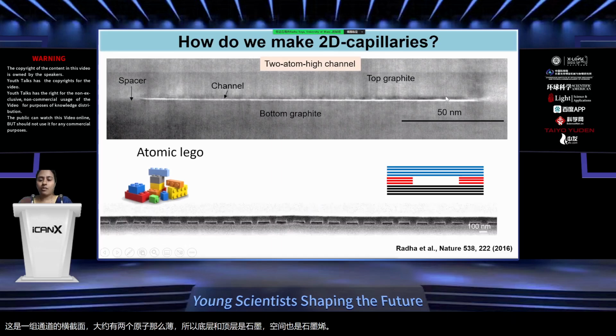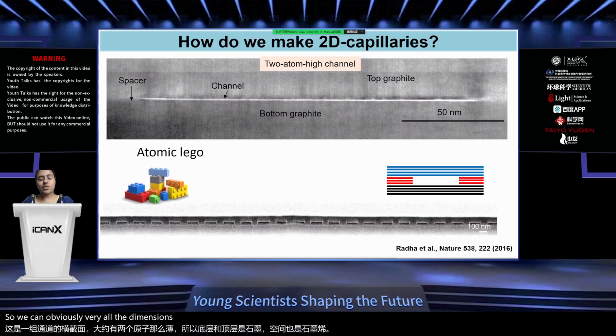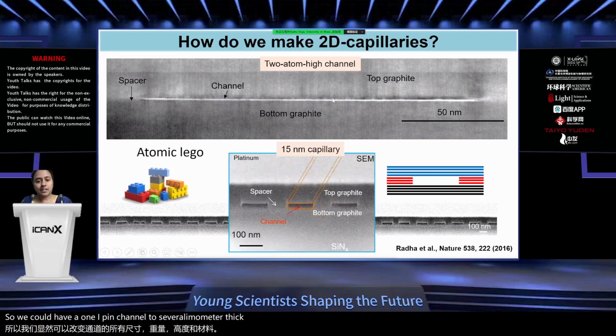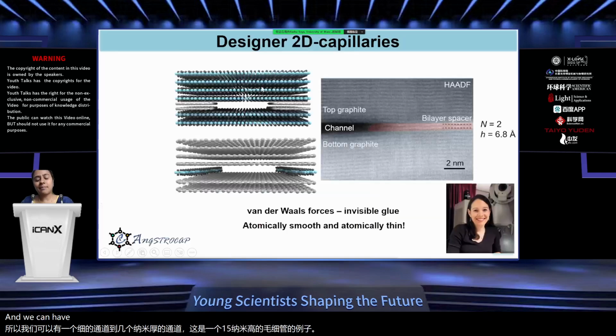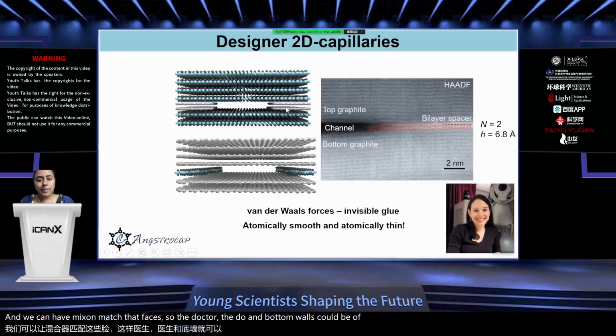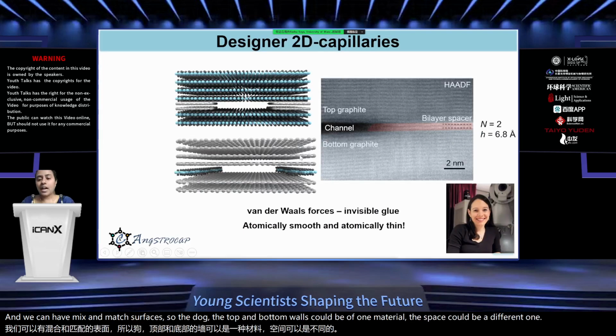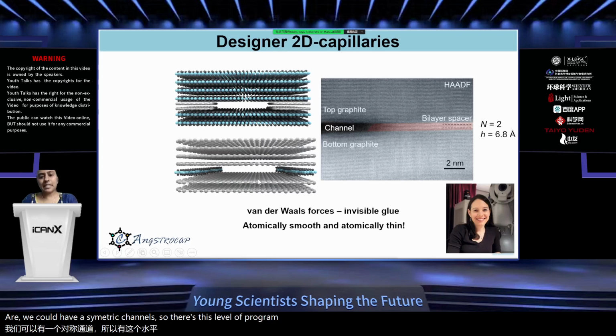So we can obviously vary all the dimensions of the channel, the width, the height, and the materials. So we could have a 1 atom thin channel to several nanometers thick channels. So this is an example of 15 nanometer tall capillary. And we can have mix and match surfaces. So the top and bottom walls could be of one material, the spacer could be a different one, or we could have asymmetric channels. So there's a level of programmability in these channels.